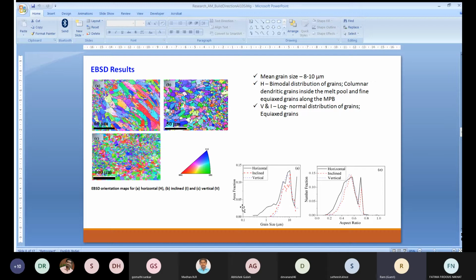Coarser grains are columnar in nature, which are found inside the melt pool, and at the periphery we find very fine, equiaxed grain sizes. So it is called the bimodal grain distribution. Whereas in the vertical and inclined directions, you have a log normal distribution of the grains, mostly equiaxed grains. And compared to the grain size, the horizontal direction has much finer grain sizes.